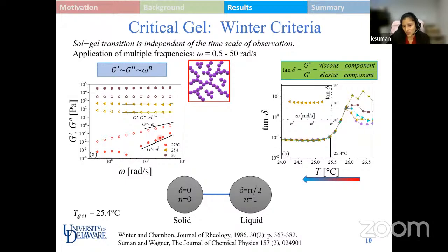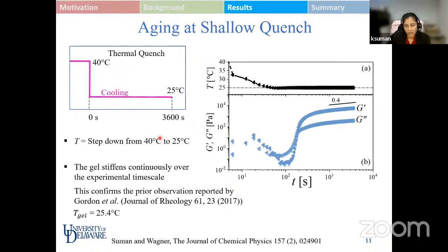Having characterized the gel point temperature, we now study what happens to this system when subjected to a shallow thermal quench. As I said already, the shallow thermal quench has been studied in the literature. The objective of this experiment is to be consistent with the literature and see if the system follows it or not. When we change the temperature suddenly from 40 degrees to 25 degrees, where 25 degrees is quite close to 25.4, the gel point temperature, we see the evolution of modulus as a function of time over here.